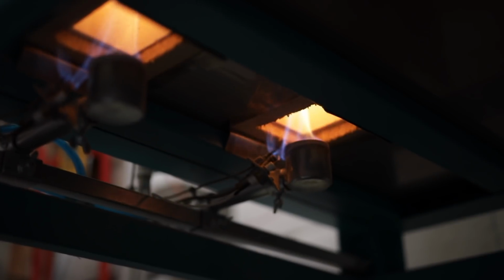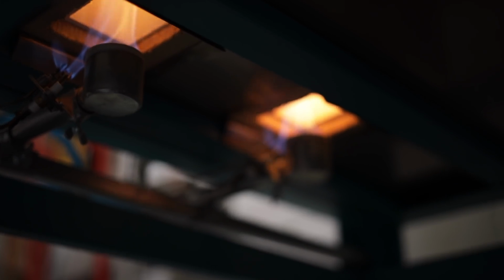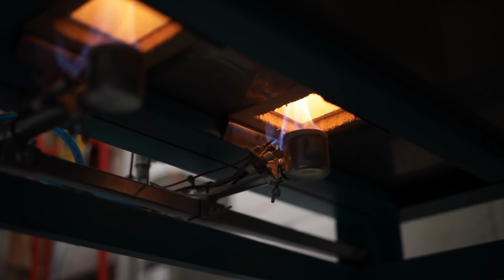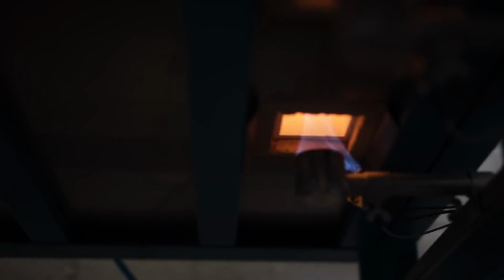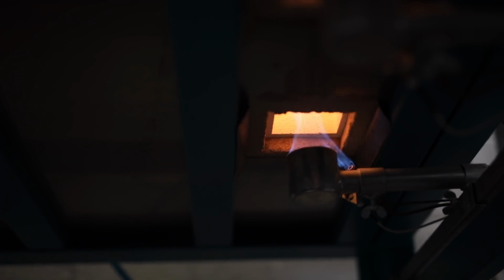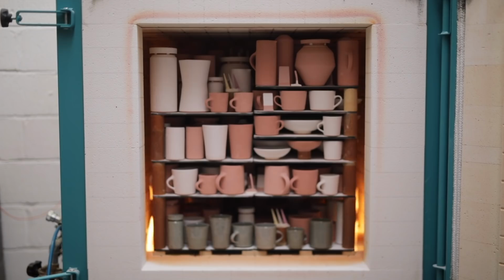And quite importantly, I'm lighting the kiln with the door open, which is a step that was drilled into me as a student, as if you light the kiln with the door closed, there is a chance it can quite literally blow up if something goes wrong. And I have in the past had to repair a kiln that had blown up. The force of the explosion bulged out the brick walls and really caused quite a lot of damage, enough so that the entire brick kiln had to be rebuilt.